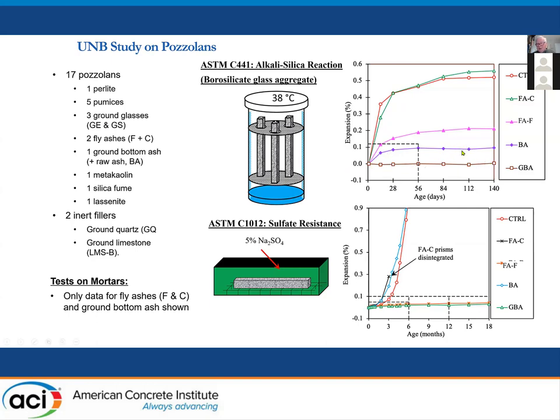Even the unground bottom ash did fairly well, but with the ground bottom ash, there's absolutely no expansion after almost 6 months in this test, whereas the control's gone much higher. And in sulfate resistance, the ASTM 1012 test, the ground bottom ash is performing very well, whereas the unground bottom ash, of course, didn't because it's so coarse, it's not reacting.